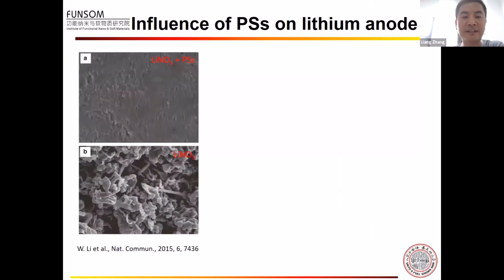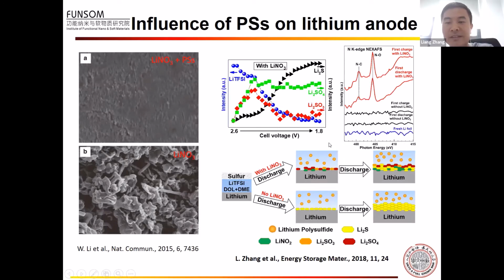Actually, lithium polysulfide can not only influence the cathode but also the anode. For example, the lithium polysulfide can react with the lithium nitrate to inhibit the formation of lithium dendrite. We also performed the in-situ XAS experiment. We found that the lithium nitrate and the polysulfide can react to form a protection layer on the lithium surface. The layer is mainly composed of lithium sulfate and sulfide, and this layer can stop the reaction between the polysulfide and lithium metal.